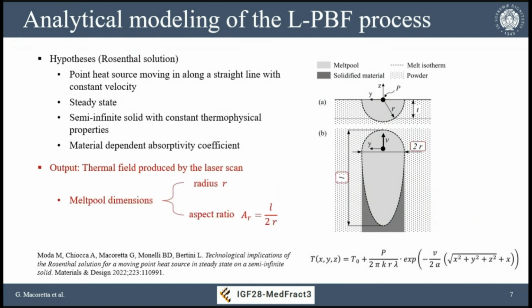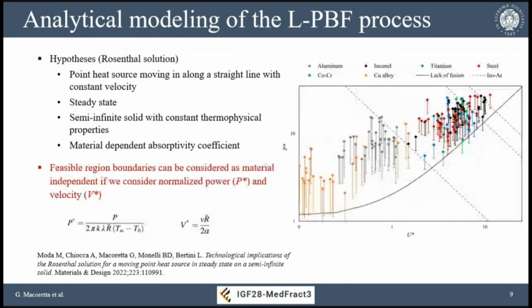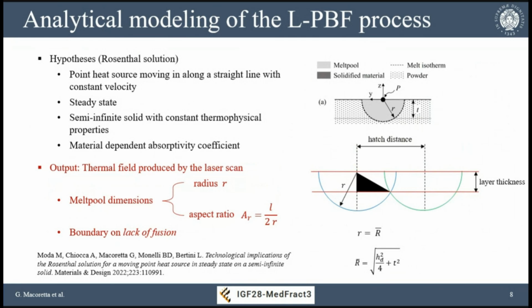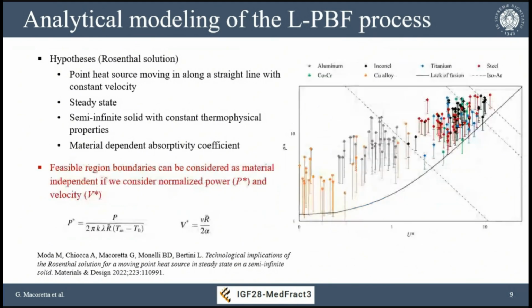What we can obtain with this model is a prediction of the radius and aspect ratio of our melt pool, so the width and length of the melt pool. Based on that, we can predict the occurrence of lack of fusion, based on the fact that we need to have at least a melt pool radius that matches the minimum dimension based on the layer thickness and the hatch distance that we are using.